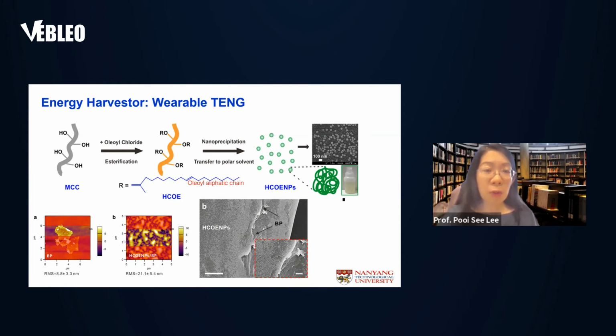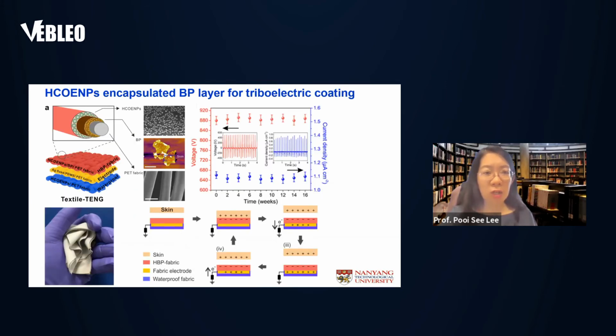This hydrophobicity is very useful because it can protect a lot of new materials from undergoing degradation or absorption of moisture. One example is the 2D black phosphorus material, which has very good electronic semiconducting properties. However, the pain point for black phosphorus is often the photooxidative degradation. And we have now used the particles to protect the black phosphorus, providing a stable bilayer structure.